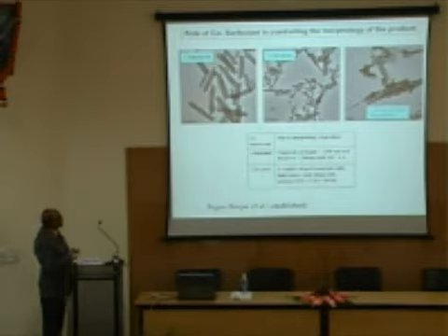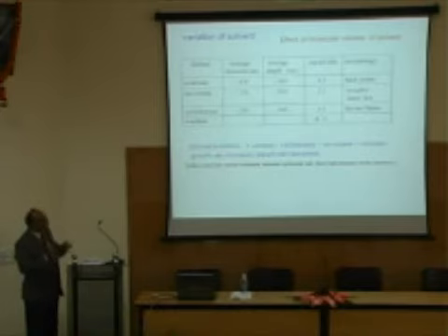Okay, so controlling the nanostructures can be done by this method easily. This is again by changing co-surfactant, you can go from longer, higher aspect ratio to smaller aspect ratio. So I will not go into this. It is more chemistry. Why does the aspect ratio change? That question. So that depends on what is called solvent bulkiness, the size of solvent. What is happening? The solvent is interpenetrating into the spherical geometry, and all these studies you can do by some dynamic methods like spectroscopy, etc.